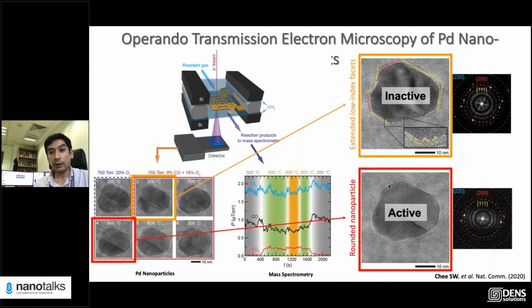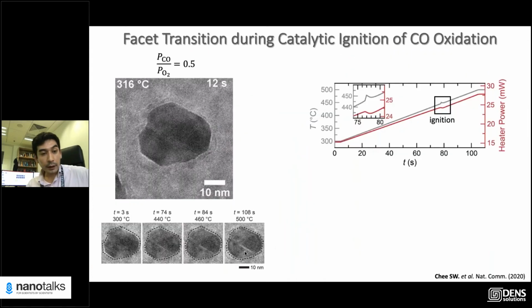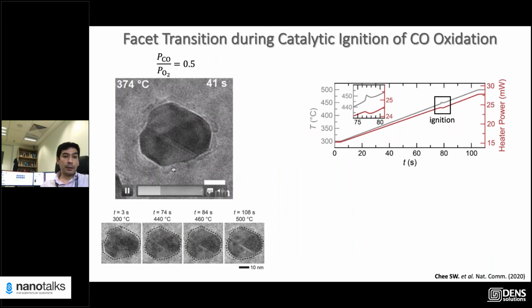So it's not faceted now, but all these edges or corners disappear, creating a lot of uncoordinated sites, and that's where the reaction actually takes place, and that's what's responsible for catalytic activity. So I'm not going to go into details, but I'll allude to it in the next few slides. But essentially, the distinct difference with the palladium here is that inactive it is very faceted and sharp, and as you increase the temperature, it becomes catalytically active, and a lot of CO2 is being produced. So this is our temperature ramp up.